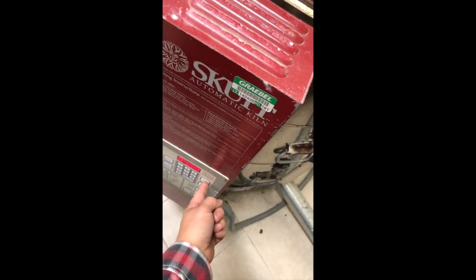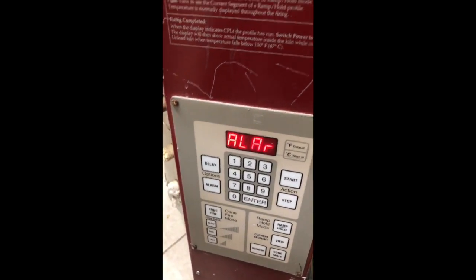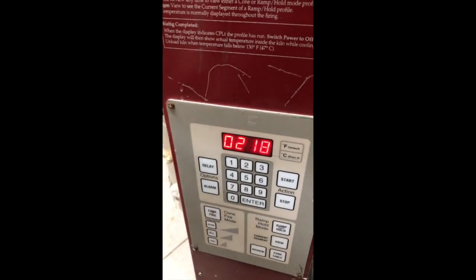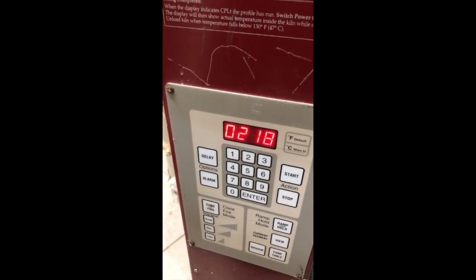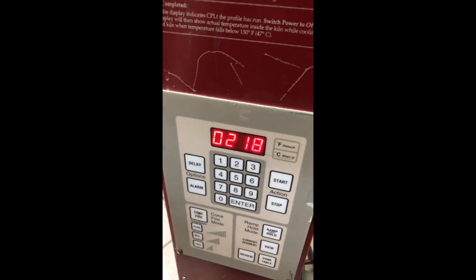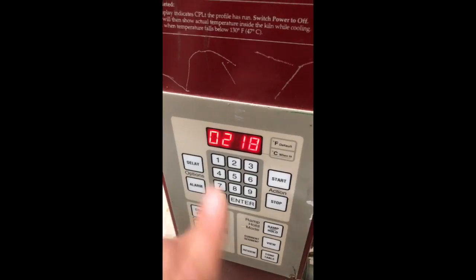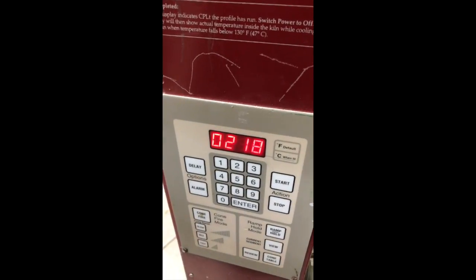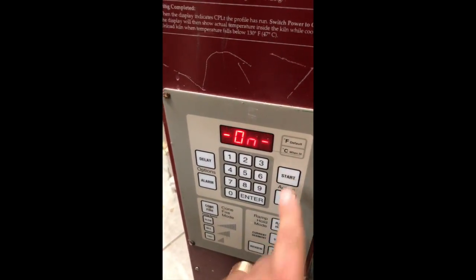I'll hit enter — wait, one more thing: an alarm. The factory always has the alarm at 999. I usually set mine at 218. So if it gets to 218 this thing's gonna beep like crazy, letting me know it's going past what I wanted. When elements shut off at 200, there's gonna be a little bump before the temperature drops, because there's still heat coming out of the elements and the brick around it. So I give it a little bumper.